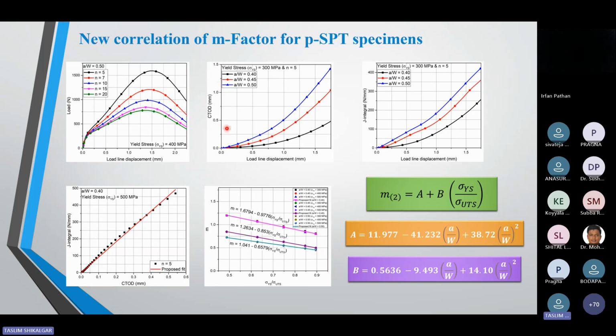Similarly, I calculated CTOD versus displacement. Here you can see that my CTOD is increasing as my a/W ratio is increasing. Similarly, I calculated J integral versus load line displacement for a similar specimen. This I calculated with the help of commercial software. And I observed that my J integral is also increasing with increasing a/W ratio. So here I plotted the CTOD versus J integral. Here you can see this J integral versus CTOD. I observed that I am getting a linear correlation between these two fracture properties.